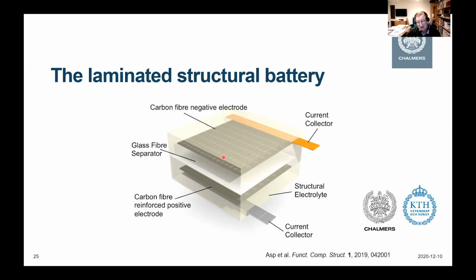We separate this to a counter electrode, which is also carbon fibers, but those are coated with a positive electrode coating. So that's lithium iron phosphate typically in our case. And we separate them with a glass fiber separator or a polymer separator. And then we take out the electrons on the other side as well. And then we have a structured battery, a working one. So this one is storing electrical energy, but it can simultaneously carry mechanical load.